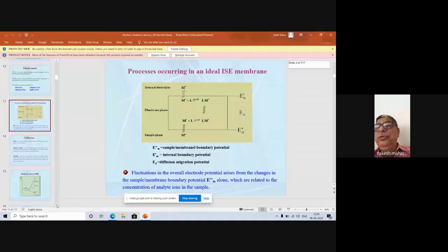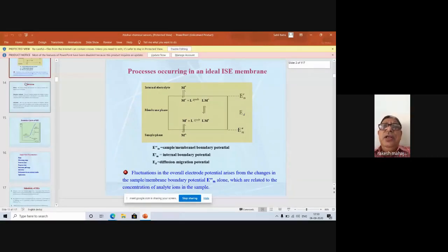This is how you can make a calibration curve. You make different concentrations of the external solutions, 10 to the minus 1, 10 to the minus 2, 10 to the minus 3 molar concentration, different beakers of external solutions of different ions, put your membrane in each solution and measure the potential. And then plot a graph between the potential and the different concentration. You will get a straight line if it is selective to a particular type of ion. Next, please.